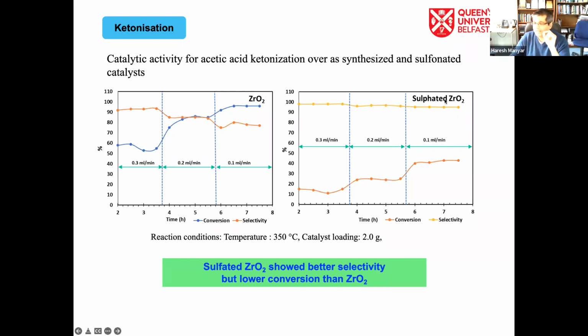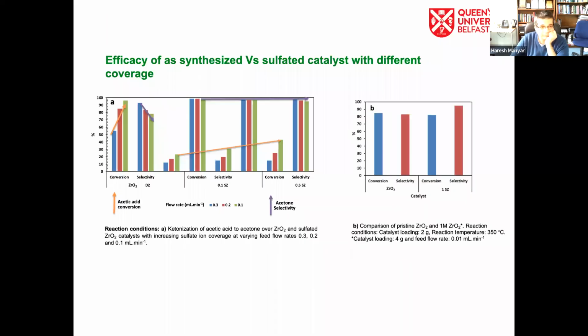So that inhibits the side reaction of the ketone, limits that reaction, and stops the formation of the byproduct. So that's where we achieve very high conversion and selectivity using the sulfated material compared to the pristine zirconium. However, we can see that the conversions are lower compared to pristine zirconium. And we will fix that as well. So no need to worry about that. We'll take care of that as well.